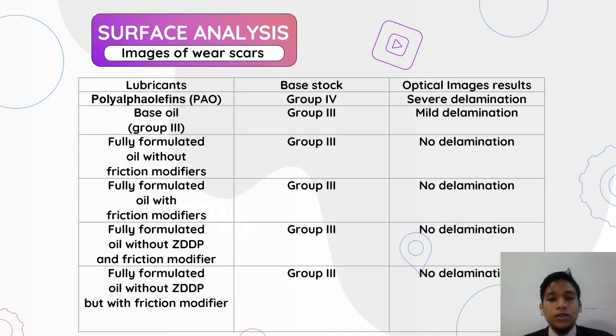Surface analysis. If the DLC coating was lubricated in PAO, severe delamination was observed in many locations, whereas mild delamination of the DLC coated plate was observed when lubricated in Group 3 base oil. In contrast, no delamination was found in completely formulated oils. Rather, the coating wear was dominated by gradual polishing wear. The term delamination used in this study refers to coating removal from the substrate.